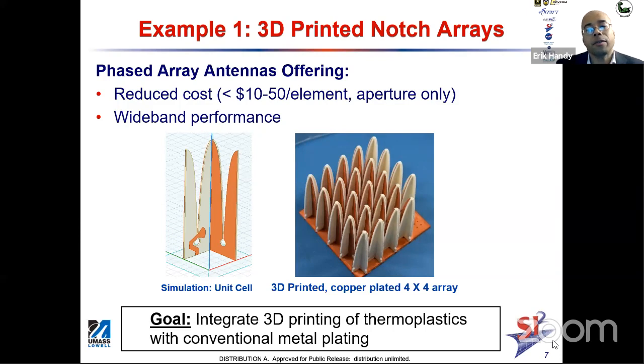So our thinking was, well, using 3D printing, can we grow that structure from the ground up and not really have to get in there with our hands and slot individual circuit cards together? So stitch them together electrically, but make sure they have the right geometry. Can we grow that structure? And then to keep costs down, can we metallize that structure in a selective way using conventional plating? So it's a merger of 3D printing for the dielectric and conventional plating, hopefully the best of both worlds.